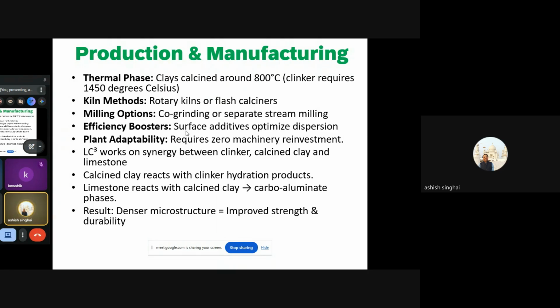So as far as production and manufacturing is concerned, it requires only 800 degrees Celsius as compared to the clinker, which otherwise requires 1450, twice of that. Kiln methods are almost the same. That is rotary kiln or flash calciner, which is being used in today's cement industry. So no separate equipment is required. Milling options: co-grinding or separate stream milling. Again, it is an existing system in all the cement organizations. No separate machines are required.